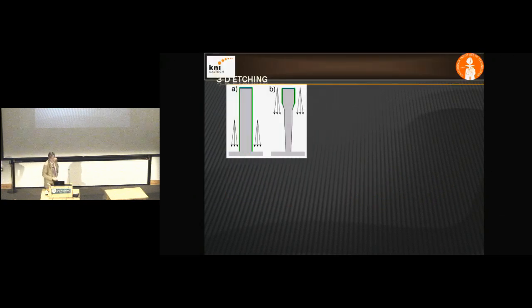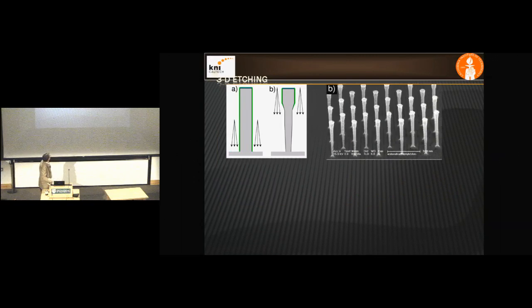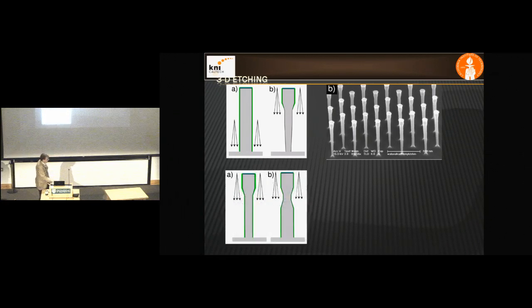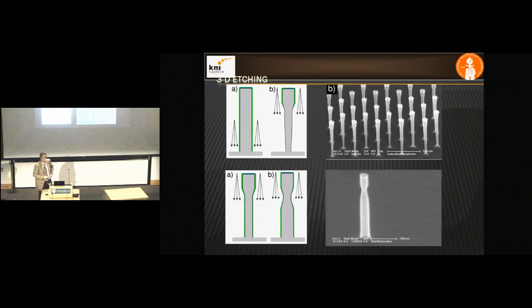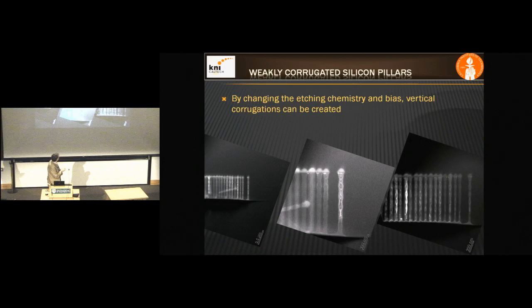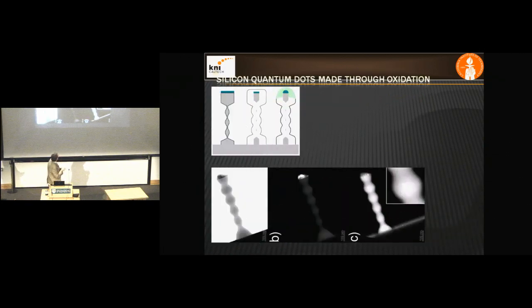Okay? So how do you do that? Well, you can etch the silicon, and you can undercut it. But if you correct that, you can go and put a dimple in it. Okay? This is now 3-dimensional. You've made a 2-dimensional object with a very small mask, but you've now made it 3-dimensional by changing the etching conditions while you're transferring the pattern down into the substrate. You can make a corrugation. It goes in and out. Okay? You can make this corrugation as wide as you want.